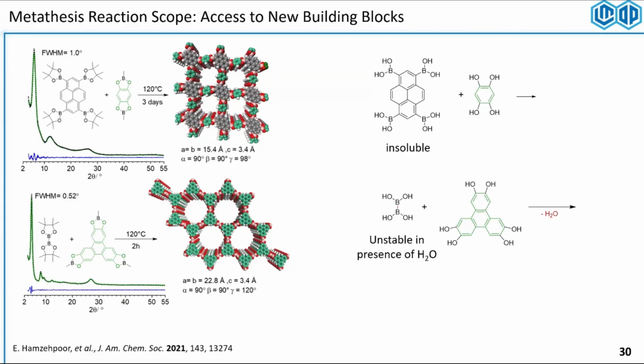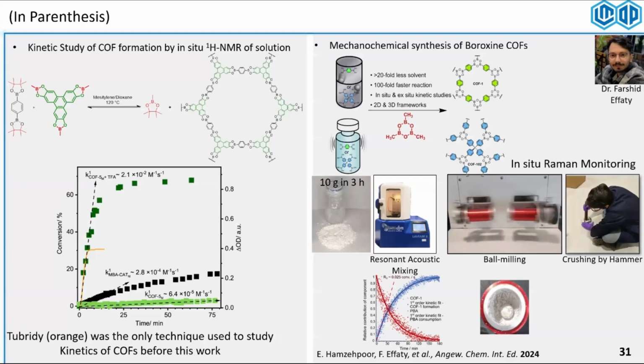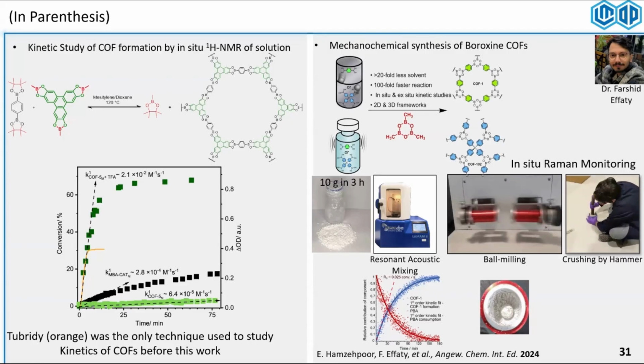And we made the first tetrahydroxy diboron-based covalent organic framework as well. And later, we studied the kinetics of the COF formation using solution state NMR, because now we had an NMR identifiable precursor that was essentially getting released into the reaction. We could track the formation of this methyl pinacolate ester and essentially track the covalent organic framework formation.